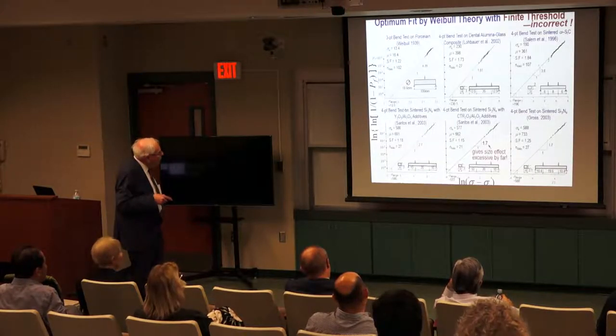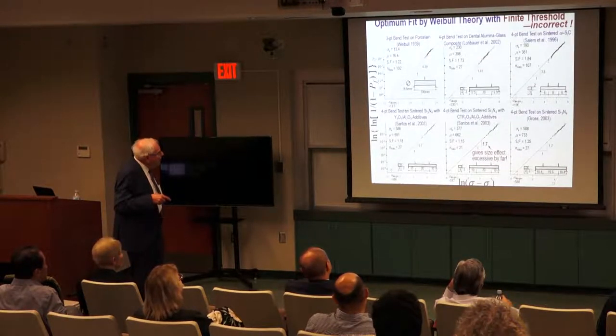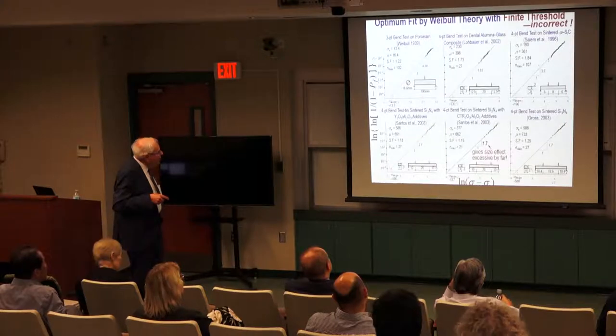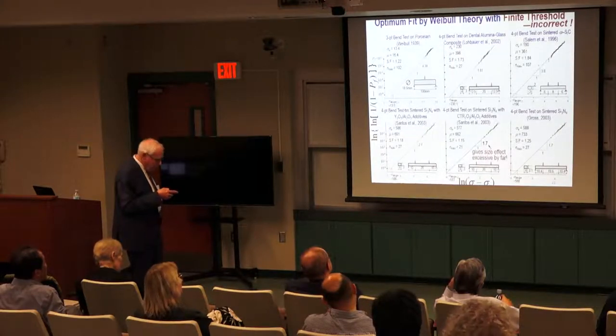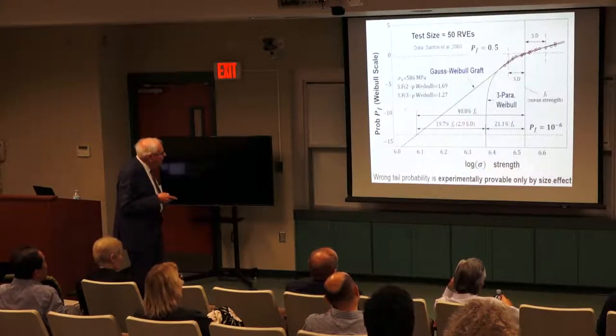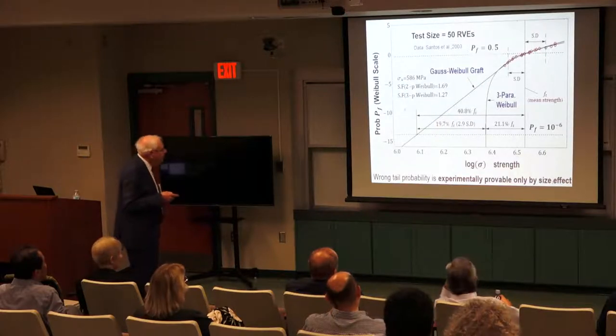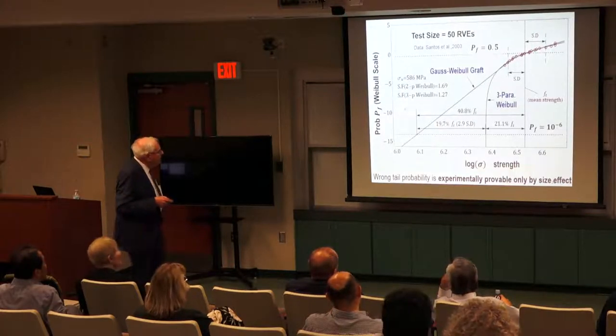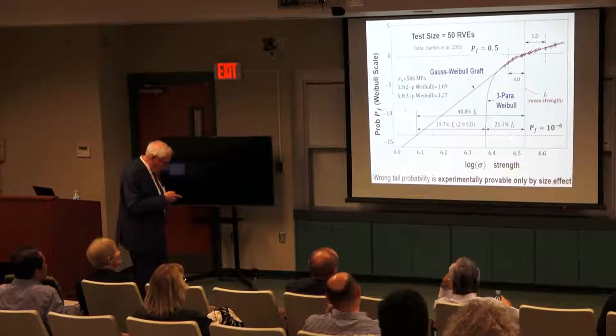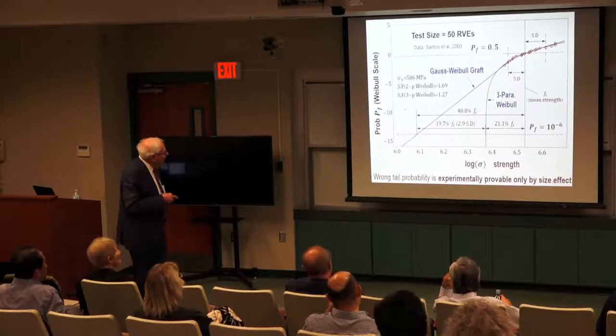Now, if they plot it in that scale, they also get straight lines. But you see how compressed these diagrams are. The coefficient of variation is actually higher. They are in principle incorrect. That can be seen if you consider extensions and if you consider the size effect. So in Weibull scale, I take this data from this picture by Santos.